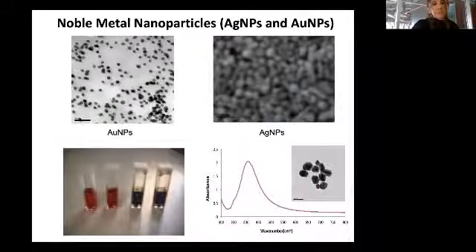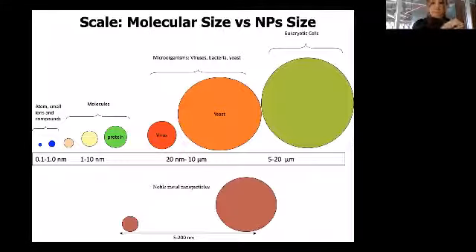So in my research, we always used silver or gold nanoparticles, okay? We can synthesize these easily, and we've been doing this for years. If you're using these nanoparticles in your research, you need to be careful with the size issue, okay? As I told you earlier, I am applying this technique in biology. In complex biological systems, if you look at the size of the structures, proteins or molecules and viruses and yeast and eukaryotic cells, the noble metal particles that we use are in the range of 5 to 200 nanometers, maybe larger.